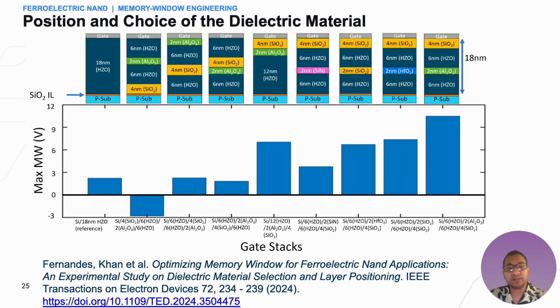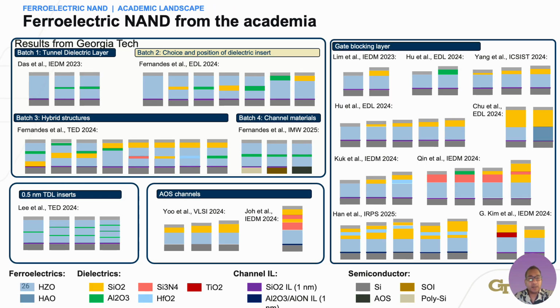We then studied how the choice of the dielectric material insert, its position, and the thickness affects the memory window. The largest memory window we could achieve was around 10 volts, which can enable quad-level cell operation. Nonetheless, the results in this slide show that there is a lot of room for engineering the gate stack for enabling ferroelectric NAND technology. This field has now expanded well beyond one stack.